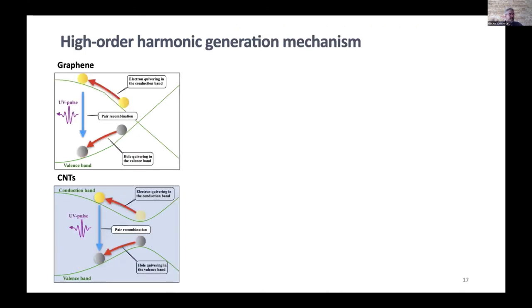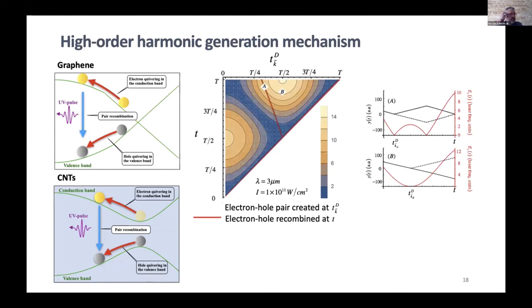To explain the harmonic emission, we have developed a semi-classical model based on the saddle point approach, which concludes that the harmonic emission takes place at instant t when the trajectories of the electron and the hole overlap in direct space, emitting a photon which is resonant with the bandgap at that instant of time. This semi-classical model is better understood by means of the following map.